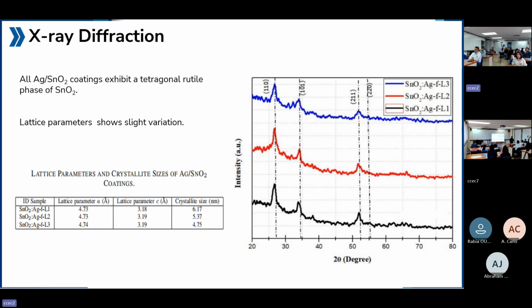On the other hand, we observed a trend of decrease in crystallite size with the addition of Ag layers, and the lattice parameter showed slight variation, which is almost negligible. This lattice distortion and defect formation may lead to a change in the surface active sites and electronic properties of the film, which can affect the gas sensing performance of the material, because these are two key factors for gas sensing.